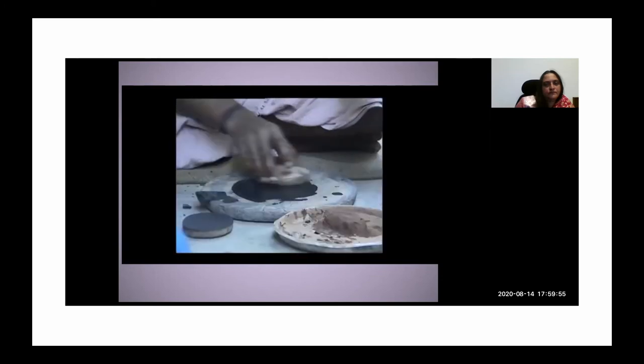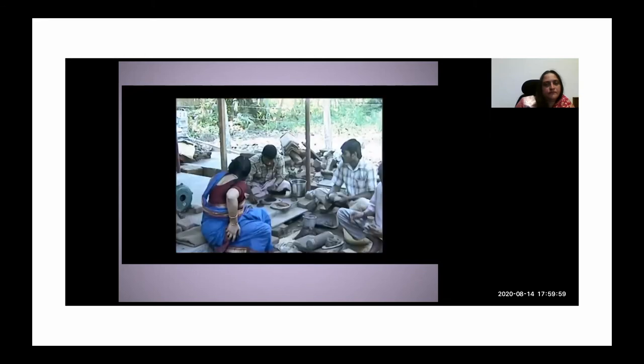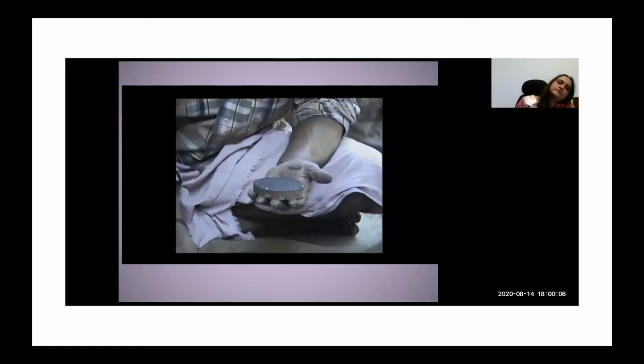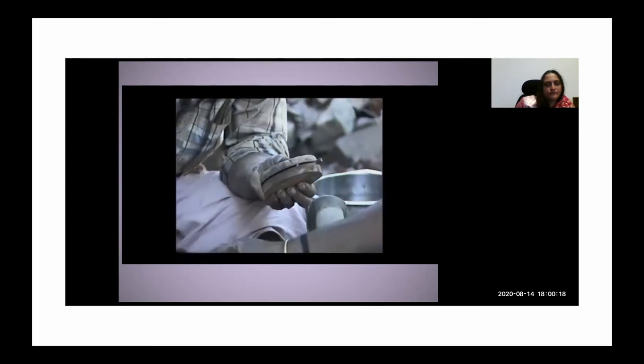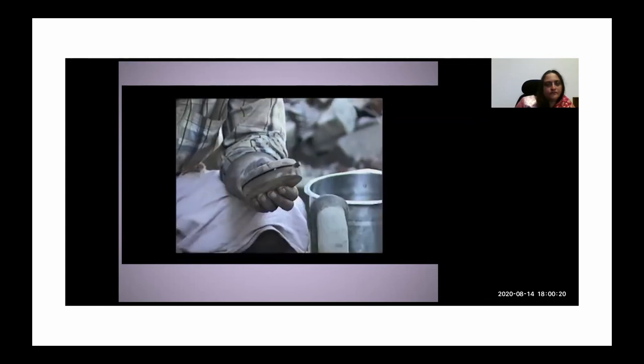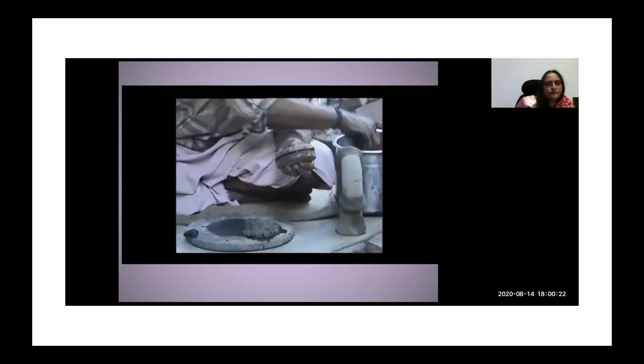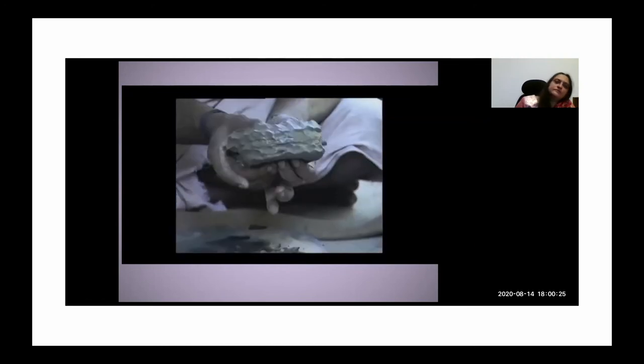So you see, it's a very fine slip which is applied on the surface of the mold. He puts these small metal spacers at the three corners. And then he covers it with the other mold. That will define the thickness of the blank. Then he will cover it with this clay which is taken from the paddy field. A fine grade of clay was made by crushing pottery.